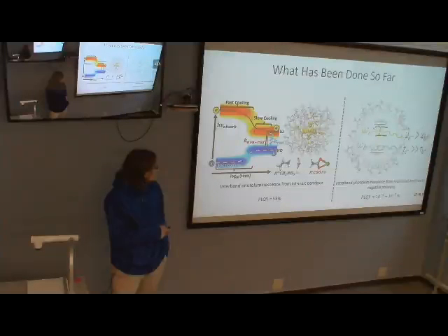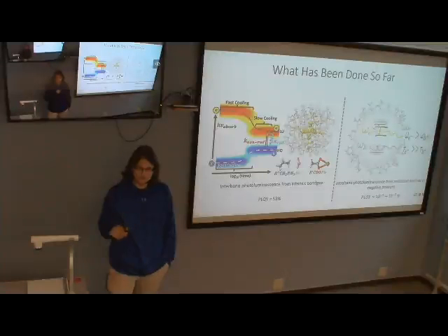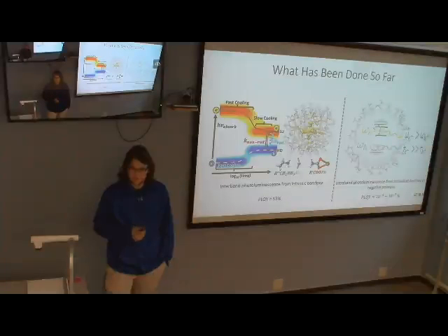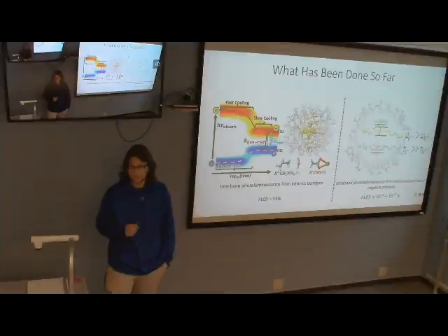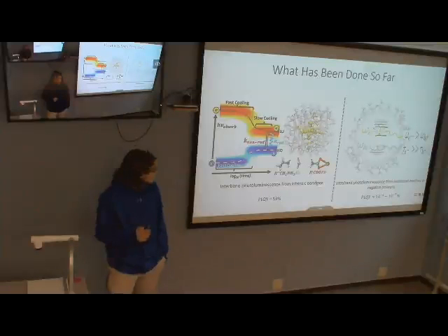But in reality, when you introduce charge into these perovskite systems, their geometries and structures will change a little bit due to polaron formation. Since they have a soft lattice, if you put an extra electron or extra hole in there, the geometry will reorganize and that will change some of the excited state properties of these systems.